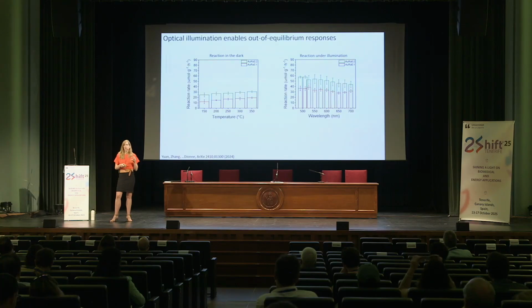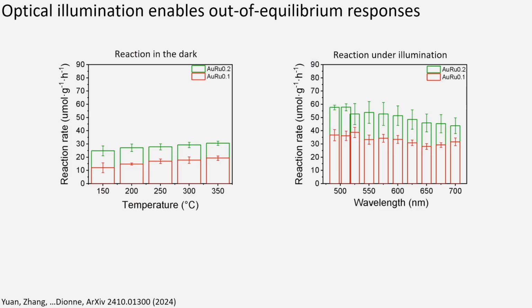And what we did is basically change the amount of concentration in our alloyed nanoparticle, with a gold-ruthenium composition that had about 20% ruthenium and about 10% ruthenium. If you're doing just thermocatalysis, the reaction in the dark, here you can see as you increase the amount of ruthenium, your reaction rate for creating ammonia from nitrogen and hydrogen actually goes up, and that's what you'd expect because you have more active sites to basically drive the reaction.